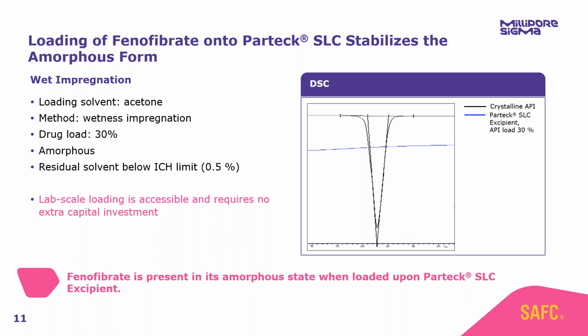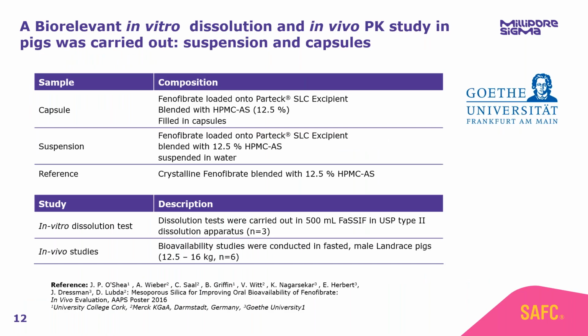Another important point is the residual solvent. We have dried, in this case, to well below the residual solvent limit of 0.5%. And this is a really important process control step to make sure that the solvent is well below the ICH limit. And this is something that you can pretty much do with no problem from this mesoporous silica. So what is the impact of this formulation on the overall performance of this BCS class 2 molecule?